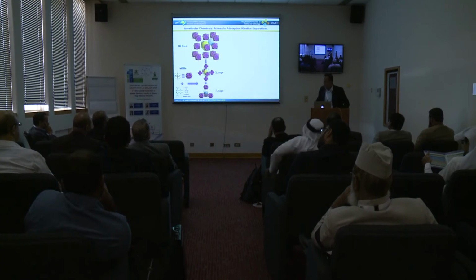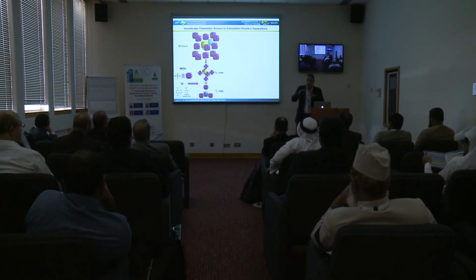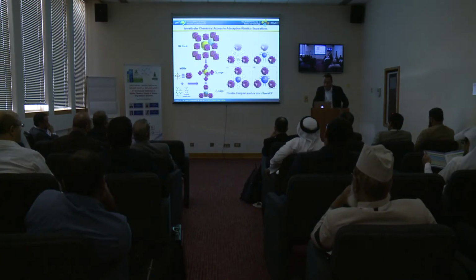But what I want to point here, when you have a platform, we talk about design, meaning that now you can actually change the properties of your ligand for a given application. This is an example here that shows, for example, instead of using the benzene here, we use naphthalene because we want to reduce the opening and access to these channels. And you can see here this is all the benzene ring in equilibrium, the naphthalene. So the pore size is getting smaller.